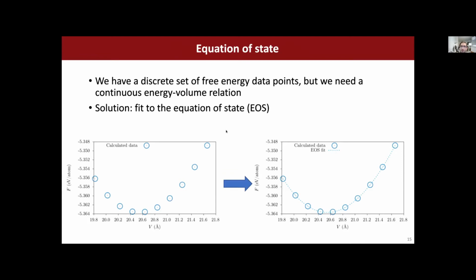However, there is one problem. We cannot do a computation for each volume. We can only do it for some finite amount. But at some point, we will need to take, for example, a derivative with respect to volume for different volumes. And to simplify our life, we can do a fitting to a so-called equation of state. Here our states are free energy and volume, and it is just some analytic form which you can use to